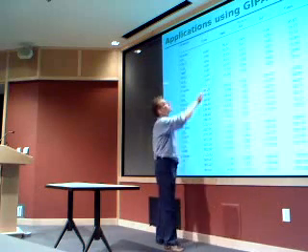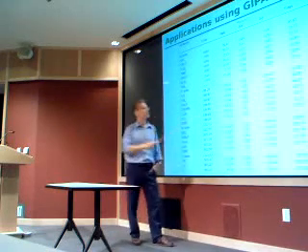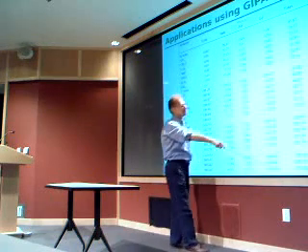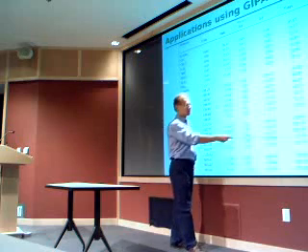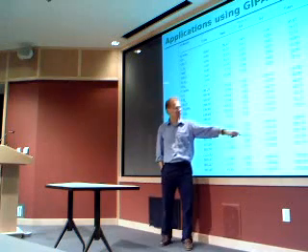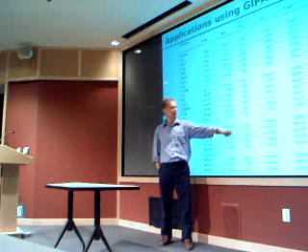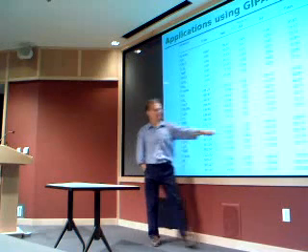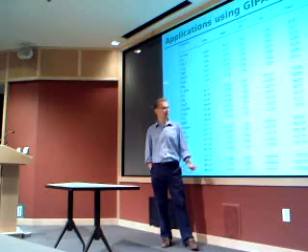So here, you have several contributions. Here the third term, the diamagnetic correction term and paramagnetic correction term, you don't need to care about these. So if you just add those up, and here's the core contribution, or contribution of the core electrons. So here's the total value. And you see that, okay, in some cases you have a value of 400, and the variation is for silicon. You have variation of even over 200. So if you have a small, here they take a constant already, but you have a difference of 0.2. So actually, it doesn't make much sense to keep so many digits.